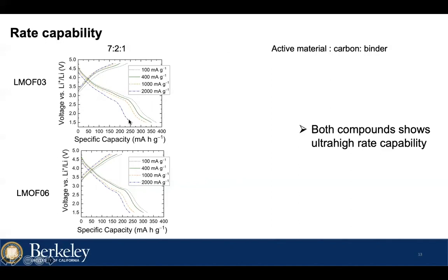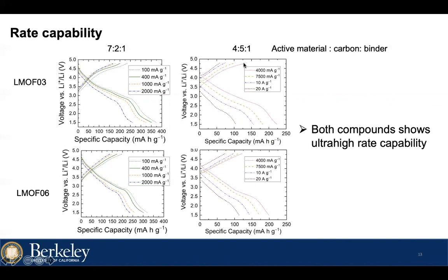Note that this means the material can finish each charge and discharge process within 8 minutes. This test was done with an electrode composed of 70% active material, 20% carbon, and 10% PTFE binder. When we further push the rate of the charge, we increase the carbon content to 50%, so we can get rid of the electronic conductivity issue and get the intrinsic rate performance from the material. And we found even at 20 ampere per gram current density, this material can still deliver a capacity over 100 milliampere hour per gram, which means the charge and discharge process can be finished within 30 seconds.